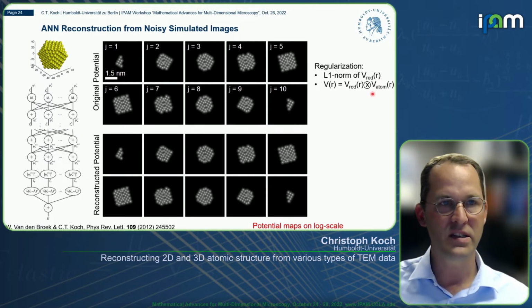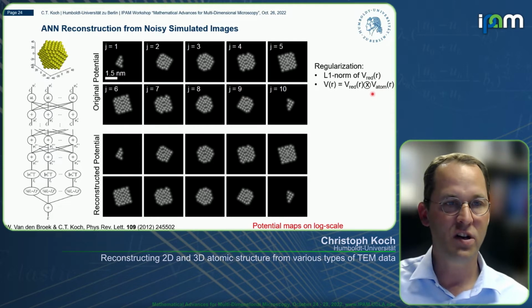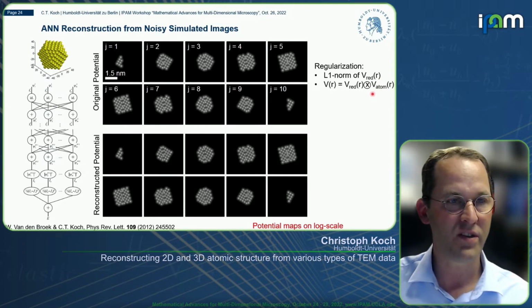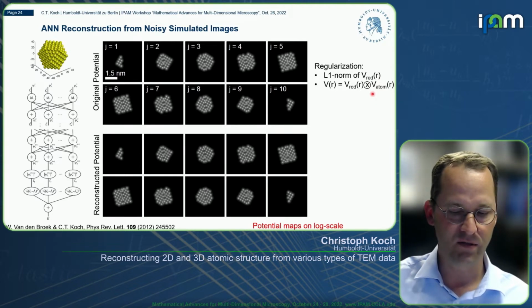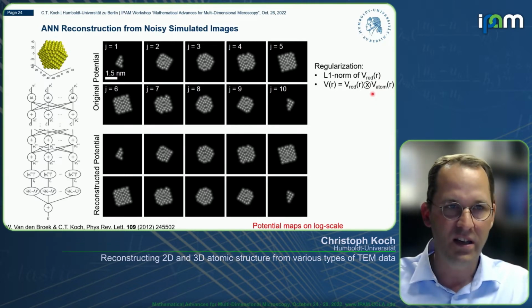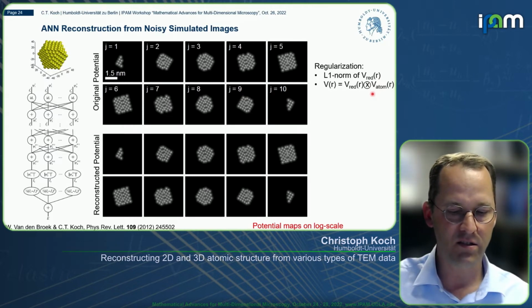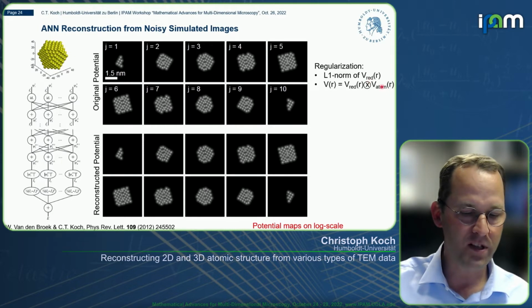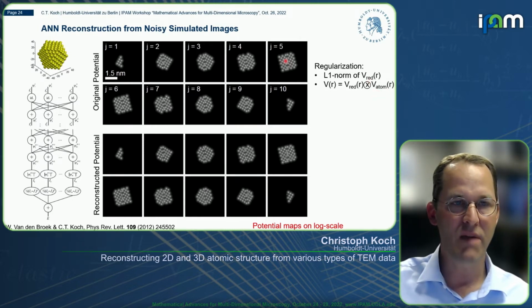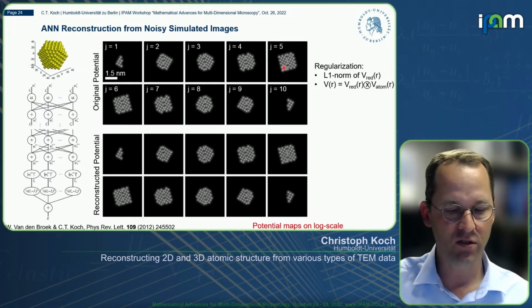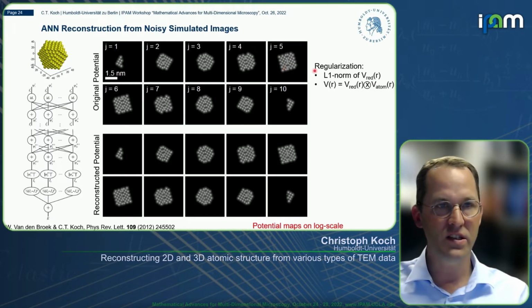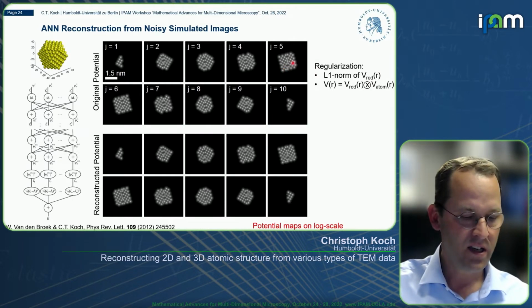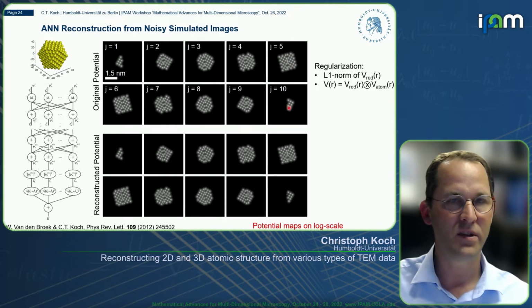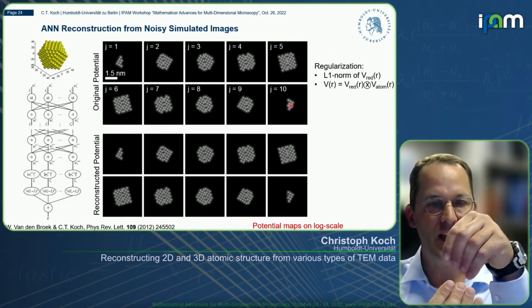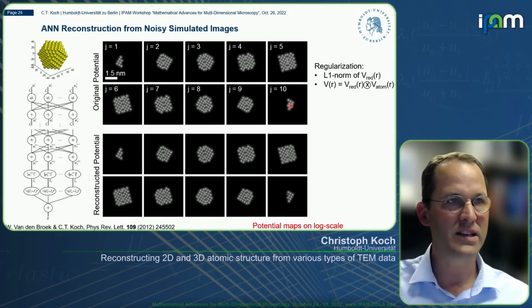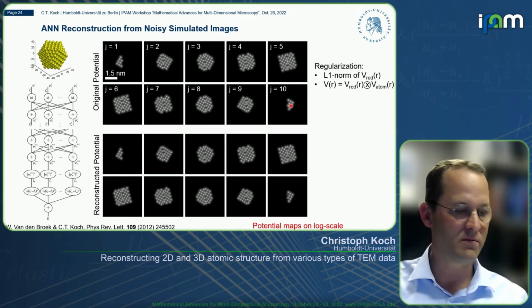And if you have multiple atomic species, you can still define a generalized atomic form factor, as is done, for example, also in direct methods that have been used to solve many crystal structures. So this is really well established, these generalized atomic form factors. But if you remove them from this potential here, you really get a delta function map of peaks. And to this, the L1 norm can very nicely be applied. Especially when you do this in 3D, that means these are now 10 potential layers that have 2 angstrom distance between them, you also don't run into the problem of having overlapping atoms. So the atoms are all nicely separated because you only look at one layer of atoms at a time.